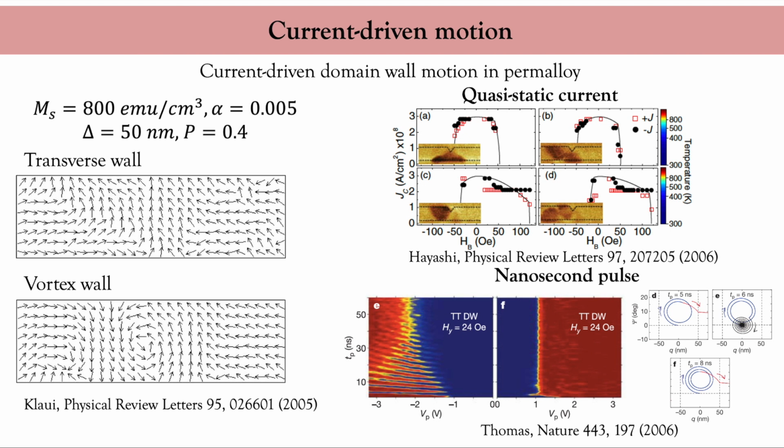What the figure says is that the depinning probability oscillates with the current pulse duration. A one-dimensional model is proposed to explain how this works. The notch constitutes a pinning potential in which the domain wall can oscillate at an intrinsic resonance frequency when excited by the spin torque. When the spin torque is turned off after the current pulse, the domain wall can reach another orbit and get kicked out of the notch.